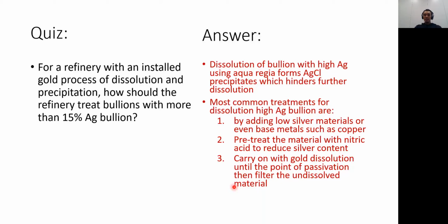And the third one is if they don't want to adapt or be creative with the circumstances. They will just carry on with the gold dissolutions until a point of passivation. So this material will be casted into granules, and then put into this digesting cell or leaching cell, and then aqua regia is added. They will do that until the granules are not dissolved again, so until it really passivates, and then they will filter it. So these three options can be done for those refineries that don't have the Wohlwill Miller process.